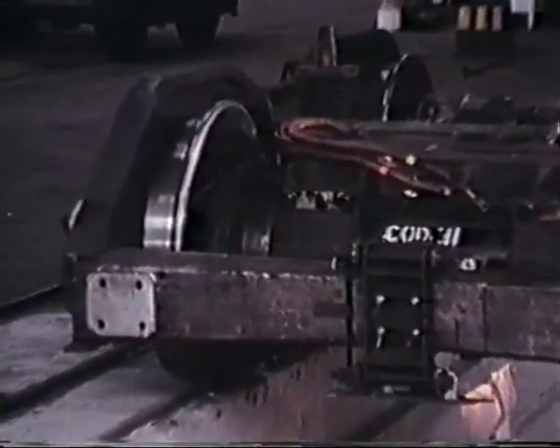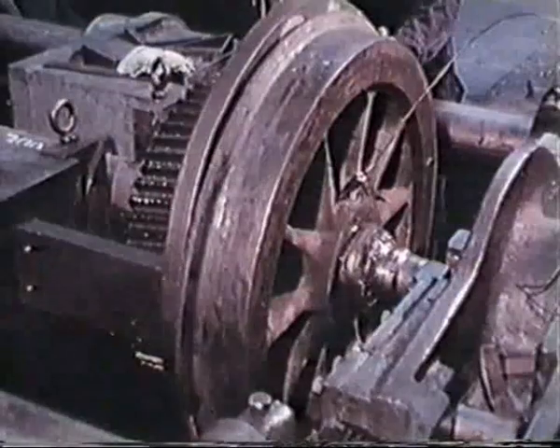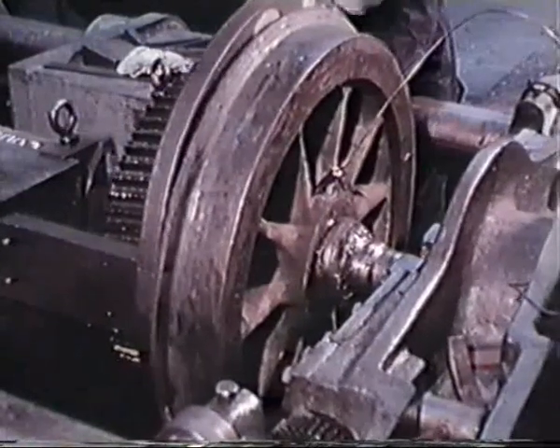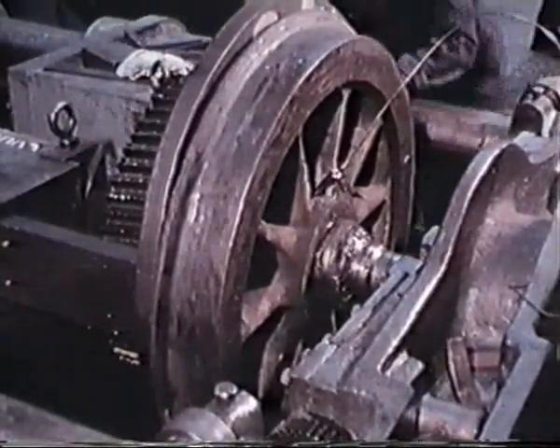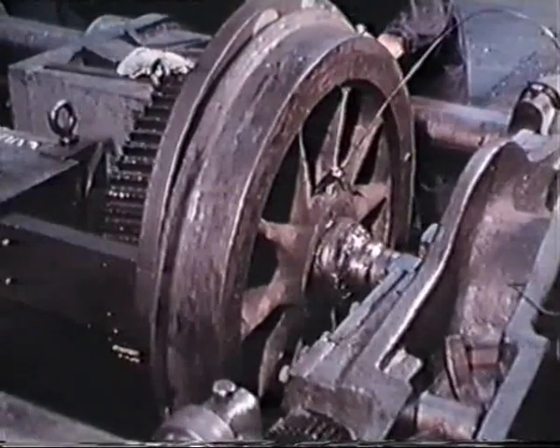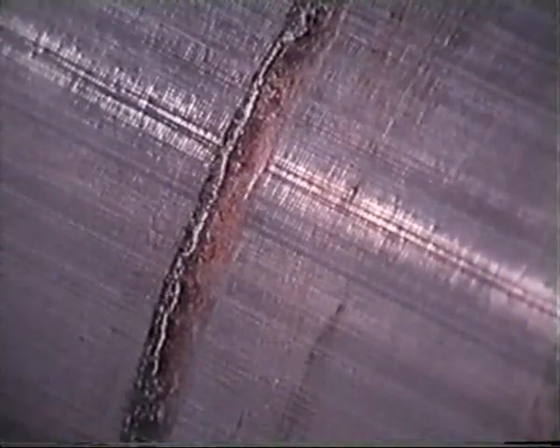Another problem of stress-assisted corrosion, with an unexpected solution, was the failure of axles on trains often working in a humid atmosphere. When the wheels were taken off, fretting corrosion, due to minute movements between the wheel and its axle, had produced a corrosion scar. The stress-raising crack associated with the scar can be found by electromagnetic detection. The fluctuating stresses during operation in the corrosive atmosphere had caused the crack to propagate, and then the axle had to be replaced after a relatively short life.